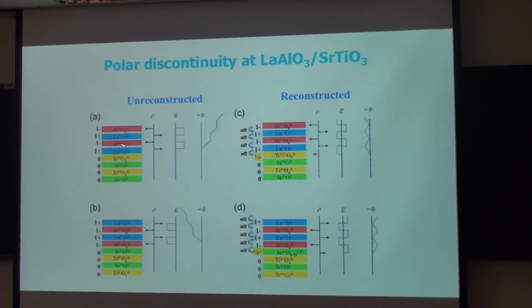As the thickness of the polar material increases, we can find the electrostatic potential associated with the electric dipole in this polar material will diverge. So, of course, this situation is not a stable situation.